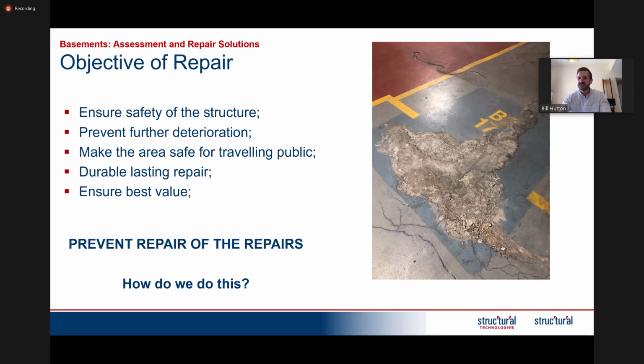We see this day in, day out, and that is repairs which are not executed properly, and that may be because the owner didn't go through the investigation stage to really understand the root cause, or maybe the concrete repairs were not carried out to a sufficient standard. This photograph on the right-hand side is a typical daily occurrence that we see. We can see that this area has been repaired. You can tell it's been repaired because you can see the paint. There's a patch around where the deck coating has been repaired. This area in the middle looks like a patch where there was an attempt at the repair, but obviously it's not a durable, long-lasting repair, and it's failed.